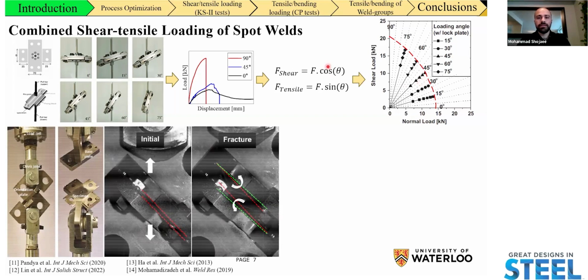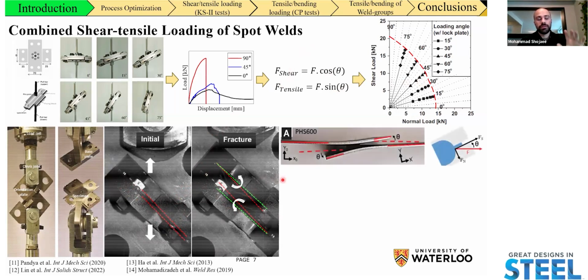Now, the issue is that the mechanical tests don't follow the initial ratio between the shear and tensile load that we intended for the whole duration of the test. I've shown an example of it here where the test is initiated at 45 degrees, and the authors actually acknowledge that we have some sort of rotation and slippage throughout the test that is changing the ratios of the load applied to the spot weld. This is also an issue with other mechanical tests, such as the standard lap shear test as well.